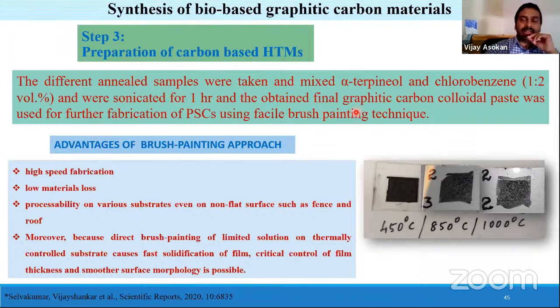Here the different annealed samples were taken, mixed with alpha-terpineol and chlorobenzene, and sonicated for 1 hour, obtaining the final graphitic carbon colloidal paste, which is used for PSC construction. We used a facile brush painting method, just like how you paint a wall with a brush. The advantages of such a method are high-speed fabrication, low material loss, and processability on various substrates, even on non-flat surfaces such as fences and roofs. Moreover, direct brush painting of a limited solution on a thermally controlled substrate causes fast solidification of the film, allowing critical control of film thickness. You can get a smoother surface morphology if you keep gaining experience with the brush painting approach. So these are our samples prepared by the brush painting approach.